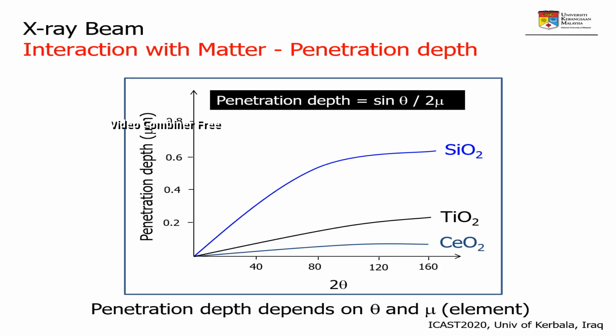Typically, the thickness of thin film samples produced in the laboratory is a few hundreds of nanometers. Every day, more and more researchers are producing films with thickness of a few nanometers. Hence, the information on penetration depth, which depends on linear absorption coefficient, is very useful for the X-ray diffraction measurement planning.